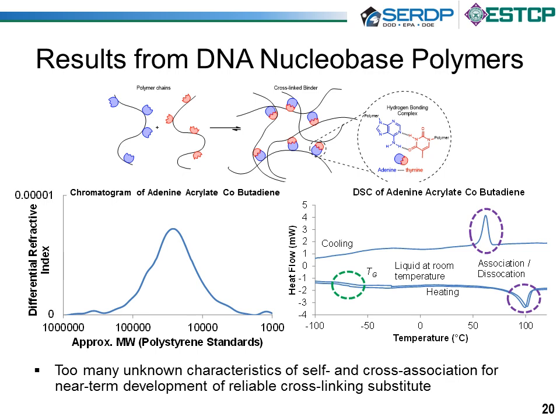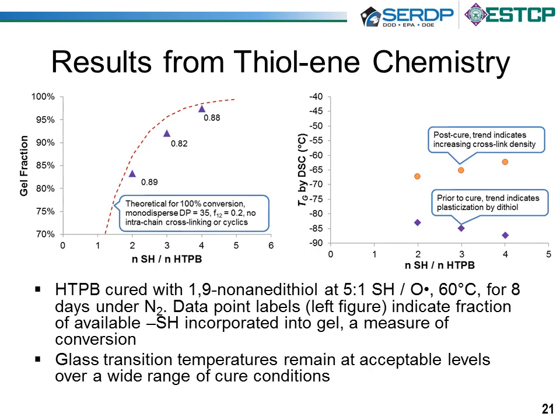An example of something that has worked for us is thiolene chemistry. This is an alternative to isocyanate chemistry, and basically we've done some testing to show that this chemical reaction will occur under the times and temperatures necessary to do the mixing of propellants. It makes the kind of networks that we expect it to make, and those networks have the physical properties that we expect out of the networks. So we're able to do some testing to confirm that the chemistry basically works, and now we're working on answering the second of those questions, which is what are the properties of the actual propellant system.